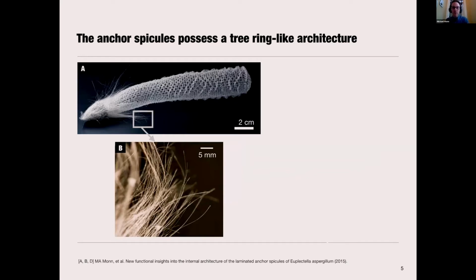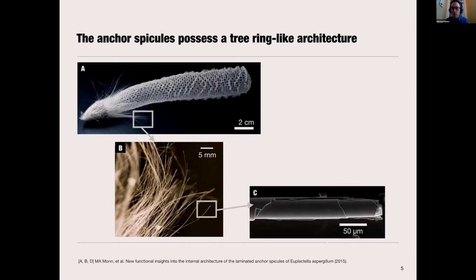And at the bottom of the sponge on the left-hand side here, that's the part that would anchor in the mud on the seafloor. You see these hairs, these hair-like fibers. Those are also glass fibers, and they act like roots. They're called the basalia spicules, or the anchor spicules, and they serve to mechanically anchor the sponge to the substrate of the seafloor so that it can pump water through its body and survive. What's very interesting is if you look at one of these spicules, they're about 50 microns in diameter, about half the width of a human hair.